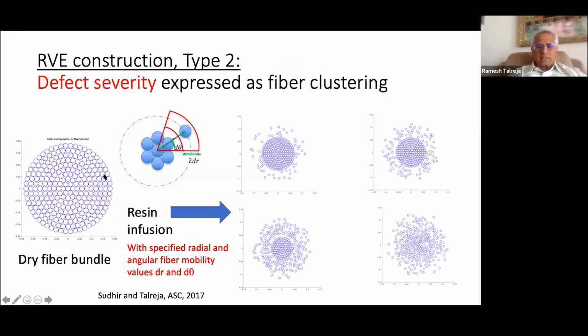Okay, the other type is where I want to see what happens to the fibers that are initially in some, say, fiber bundle in a fixed position. And as you infuse the resin, how would they create a final pattern with non-uniformity? So here what we do is we go to the central fiber, make reference there, and then go radially out and consider all the rings around it. So you're looking at the first ring here around it, and use polar coordinates r and theta, and give the fibers mobility in the radial direction as well as in the theta direction. And those two variables put together provide the mobility that you give to this bundle.